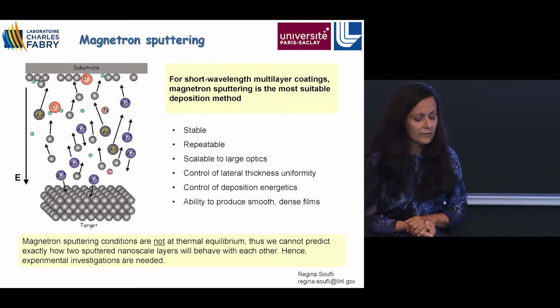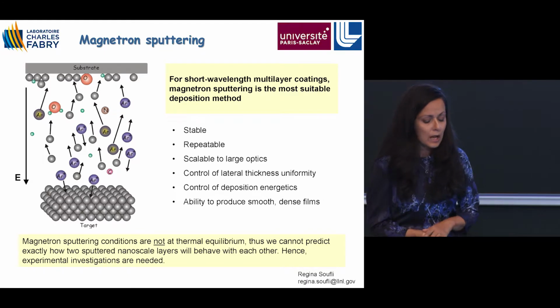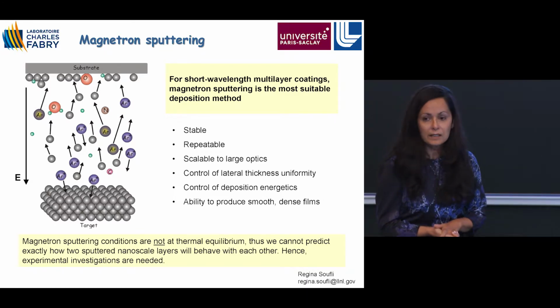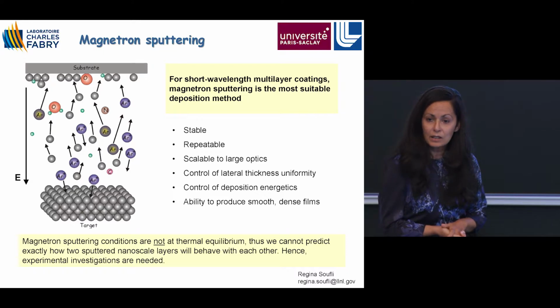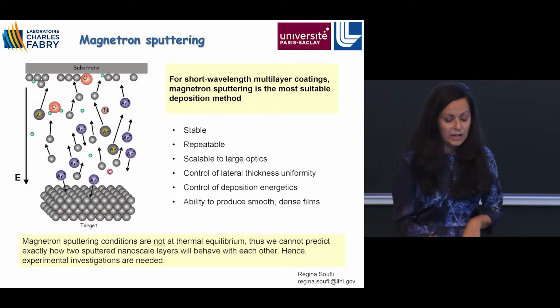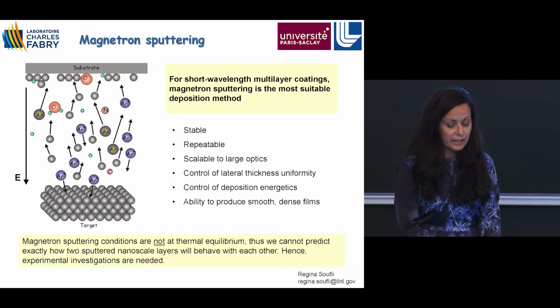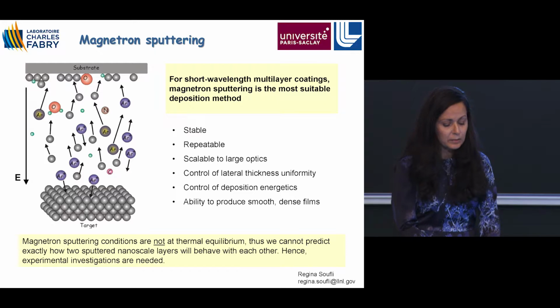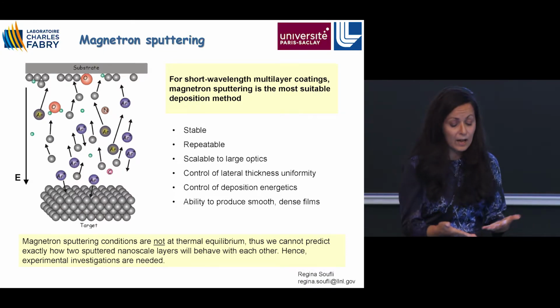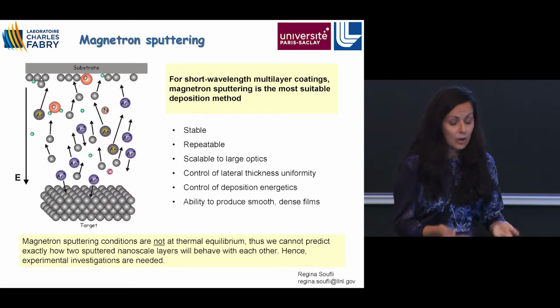So first, on the deposition facilities, we use a technique called magnetron sputtering, or in French, pulvérisation cathodique, which briefly, you have your material target that you want to deposit. You apply a magnetic field below your target. Under vacuum, you introduce a process gas. You create a plasma. And through this plasma, you get your deposition onto the substrate, whether it be a flat or curved optic or a grating or anything else that you may need to deposit on.